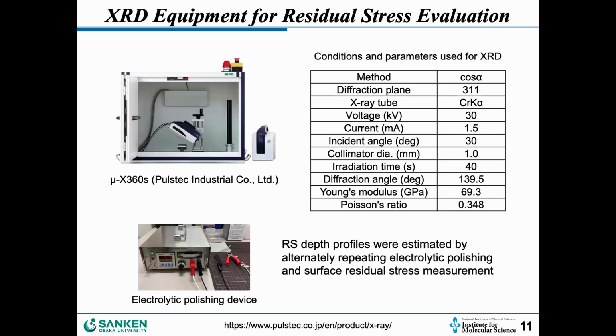At first we use XRD. This is the XRD equipment we used at Osaka University from Pulstec Industrial. The method is cosine alpha, and these are the parameters used to measure the residual stress of the aluminum alloy. The 311 plane is used, and chromium K alpha. This one is the electrolytic polishing device. We measure the residual stress profile by repeating alternately the electrolytic polishing and the surface stress measurement.